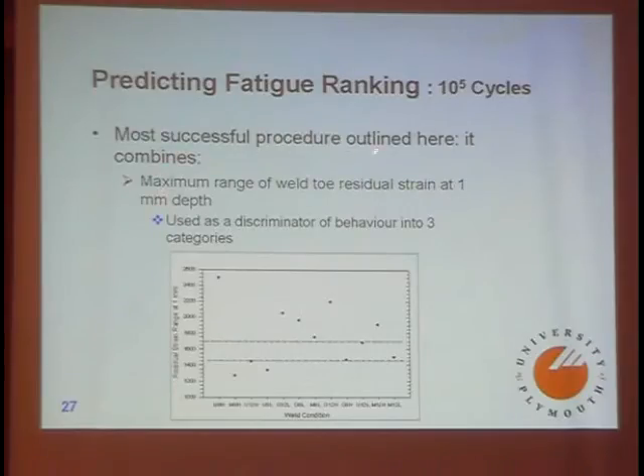So the most successful procedure takes the maximum range of weld toe residual strain at 1 millimeter depth, which is reasonable. You might expect that to affect crack initiation and early crack growth fairly well. And you can use that as a discriminator of behavior into 3 categories. So we've plotted here residual strain range at 1 millimeter against weld condition, in the same ranking order for 10 to the 5 that it should be. And you get a bunch of data up there, a bunch of data there, and some below.